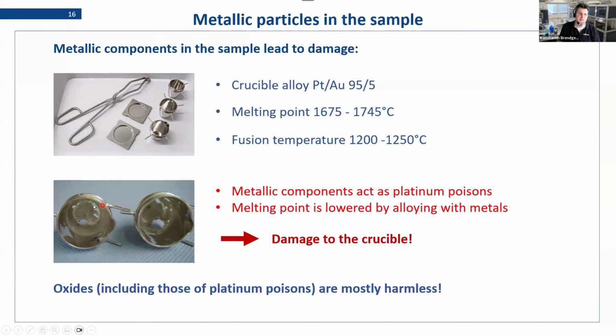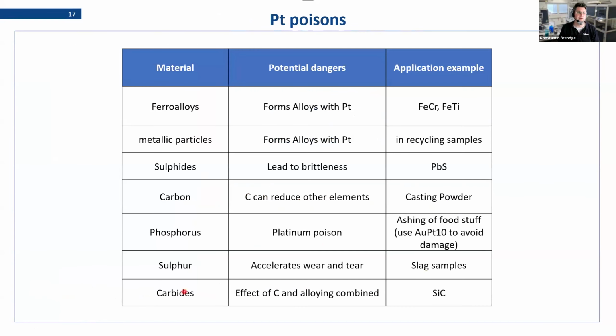And effectively, this is what happens here. Somebody did not pay attention here. They had large particles in their sample, and what effectively happens is you have this alloy forming, this effect happening, and it just eats a hole in your platinum crucible. So be careful of metallic components. Generally speaking, oxides are harmless. Even the oxides of the mentioned platinum poisons, as long as your sample is oxygen bound, in an oxidic form, that usually means it's no problem. So arsenic will be a problem. Arsenic oxide is not a problem. So one thing to keep in mind.